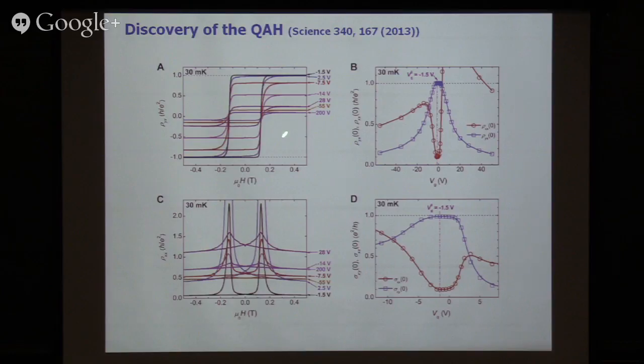The interesting thing is that you can now put the external field at 0, but sweep the gate voltage. Remember, when you sweep the gate voltage, you can go from the conduction band to the valence band through this topological insulator regime. And as they sweep the voltage at zero external magnetic field, they actually see it develops a Hall conductance plateau at 1 in units of e squared over h. At that time, the longitudinal resistance is still not quite going to 0. My colleague, David Goldhaber-Gordon, has done more experiments. It's getting very, very close to 0. It's a very precise quantization in the absence of any external magnetic field. So this is the discovery which completes the quantum Hall trio: the quantum Hall effect, the quantum anomalous Hall effect, and the quantum spin Hall effect.